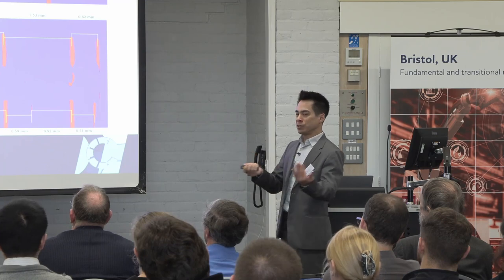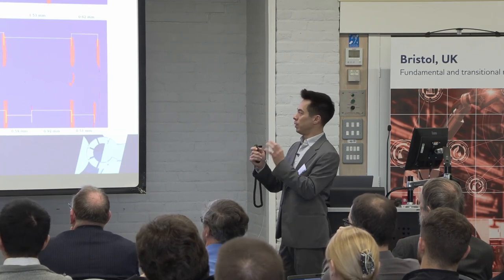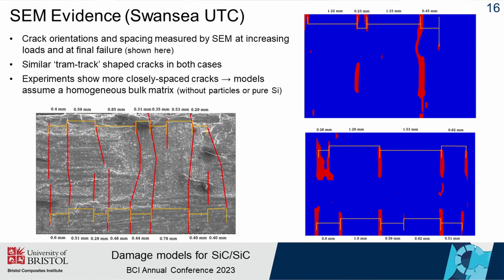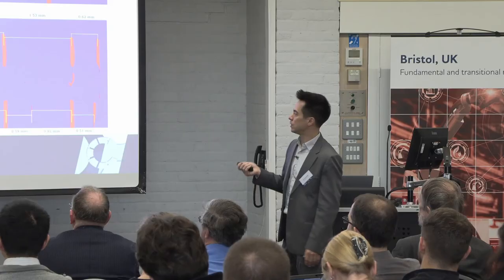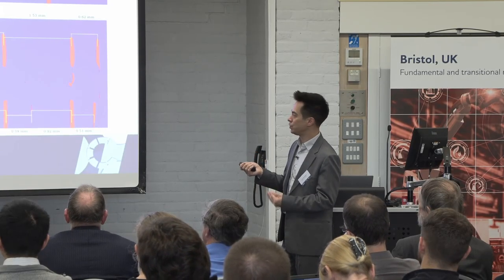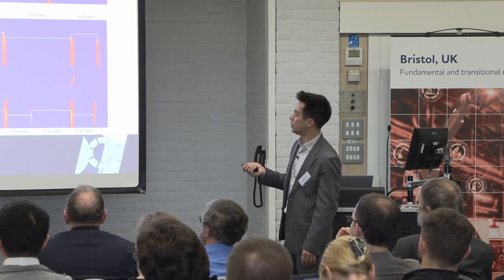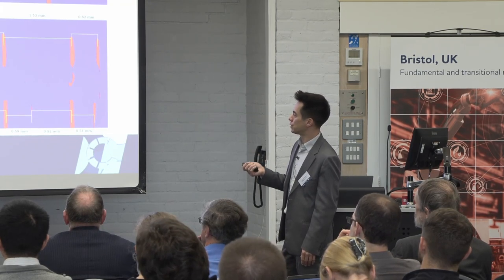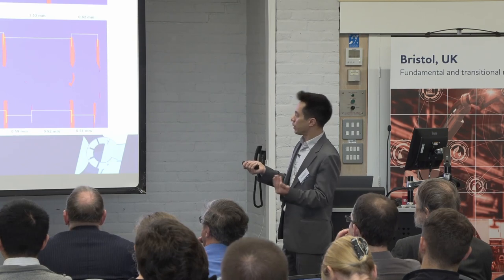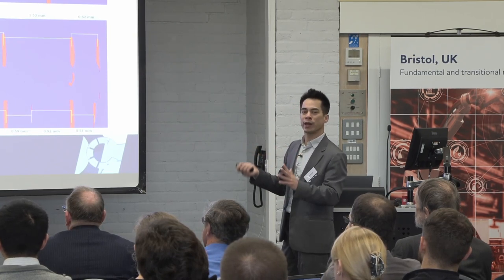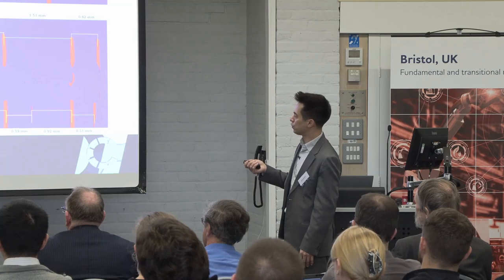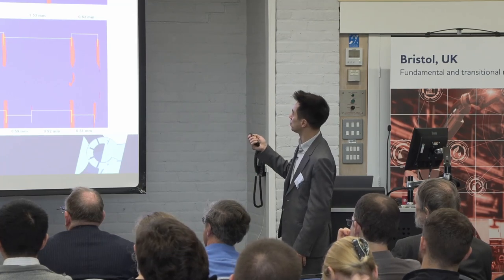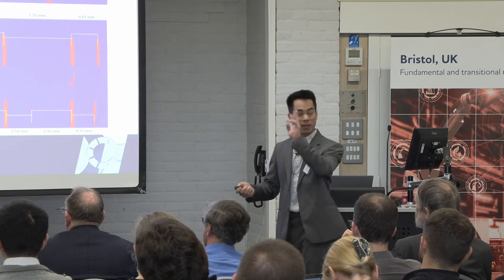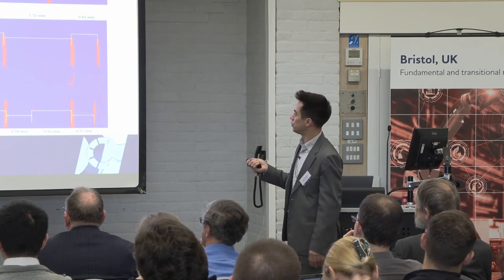So one of the assumptions I mentioned before is the homogenization of the matrix as a bulk. So it's made of different parts. We get very good qualitative agreement with experimental observations in terms of the development of this damage. These are SEM images taken by the Swansea UTC. And we see the qualitative agreement is in what we call the tram track pattern of cracks and damaged bands in the model, where these cracks and bands occur sort of in parallel.